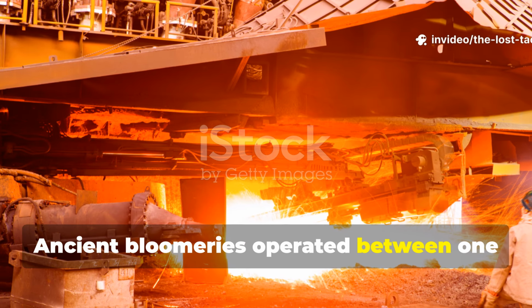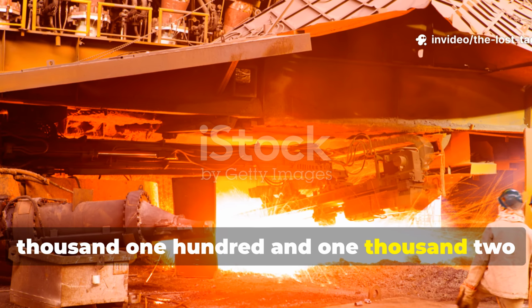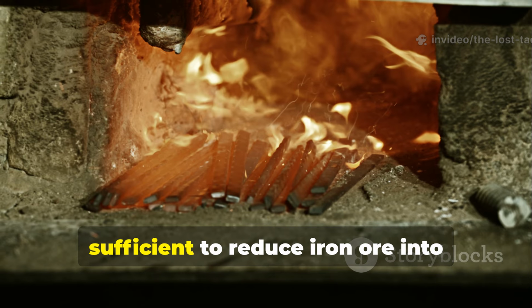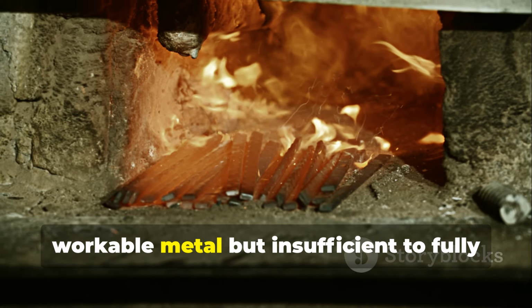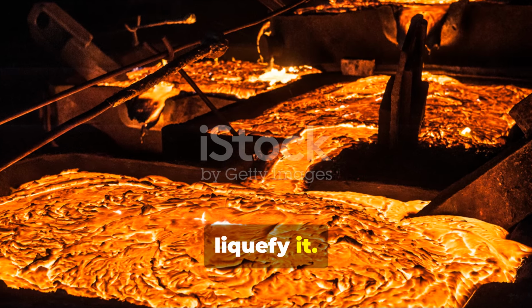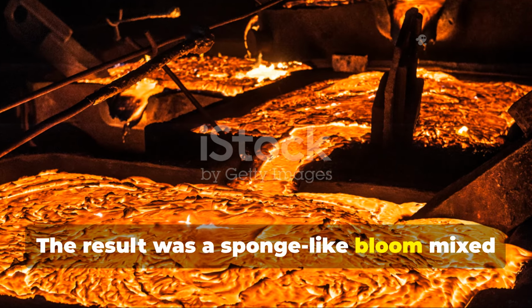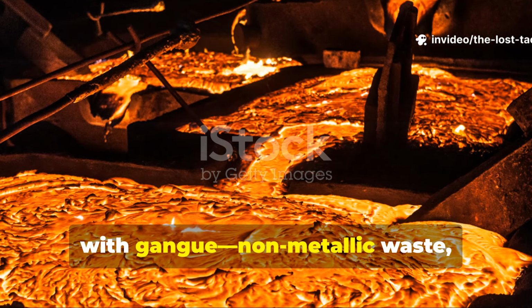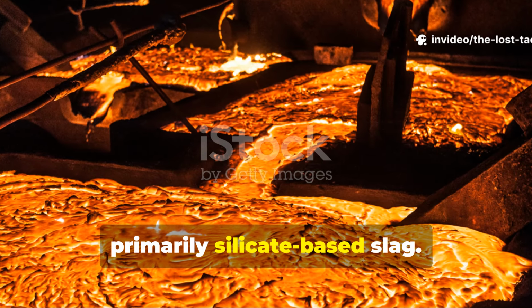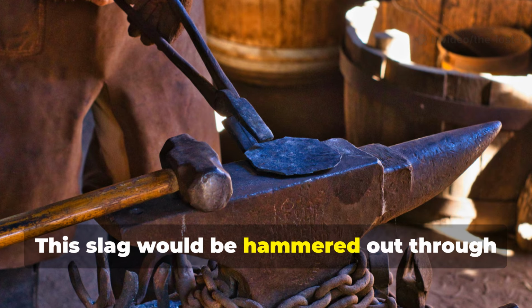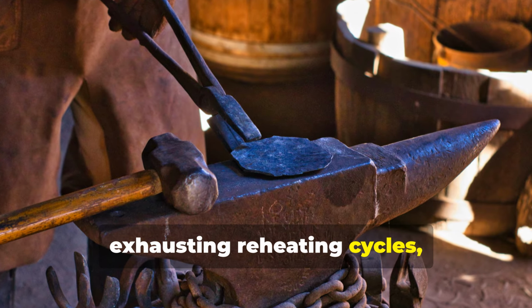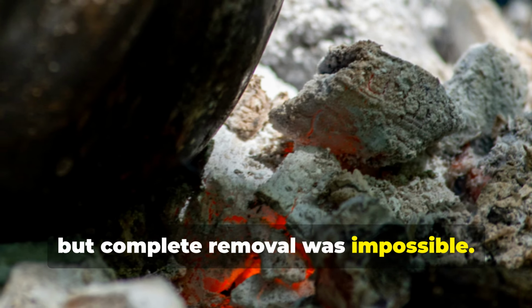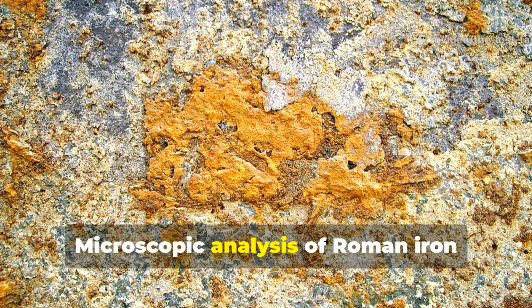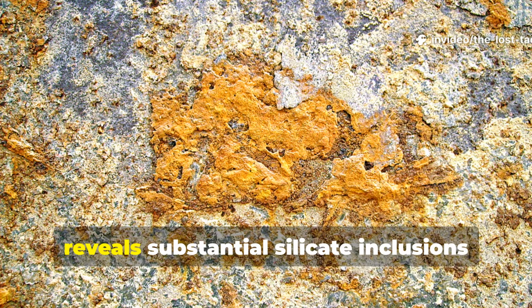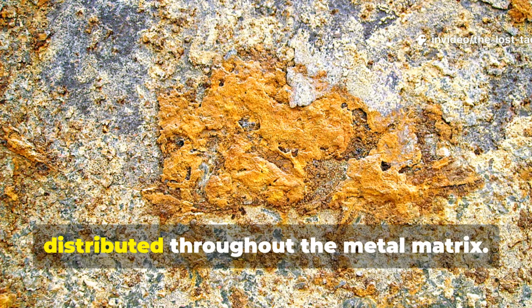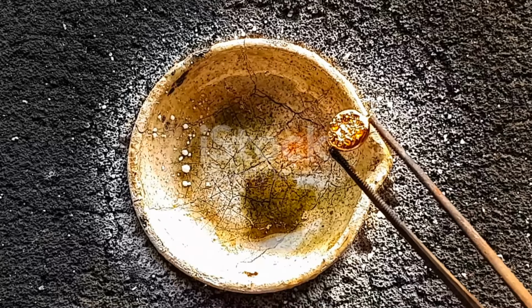Ancient bloomeries operated between 1,100 and 1,200 degrees Celsius, sufficient to reduce iron ore into workable metal, but insufficient to fully liquefy it. The result was a sponge-like bloom mixed with gangue, non-metallic waste, primarily silicate-based slag. This slag would be hammered out through exhausting reheating cycles, but complete removal was impossible. Microscopic analysis of Roman iron reveals substantial silicate inclusions distributed throughout the metal matrix.